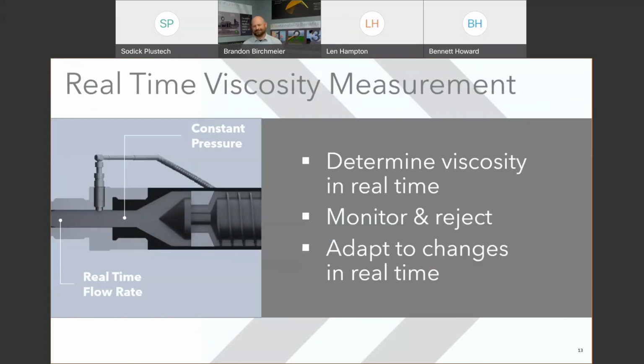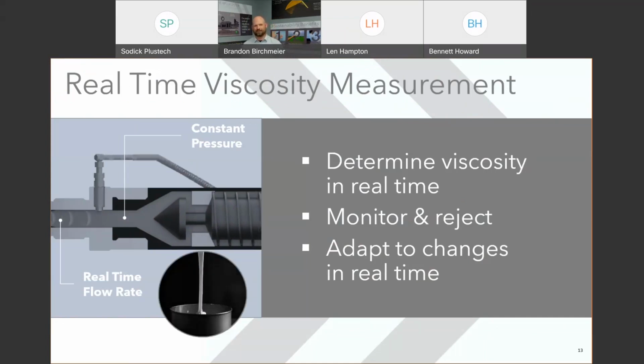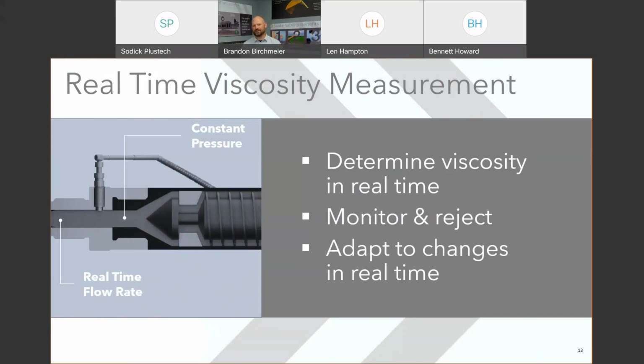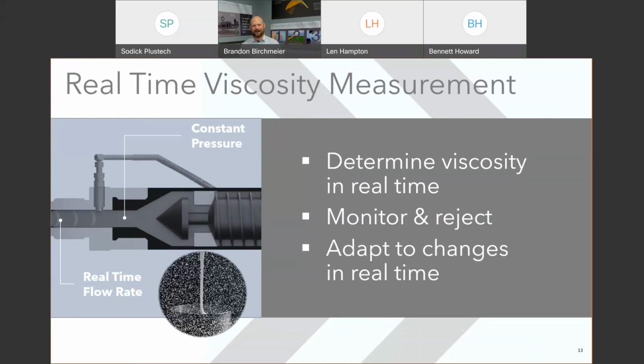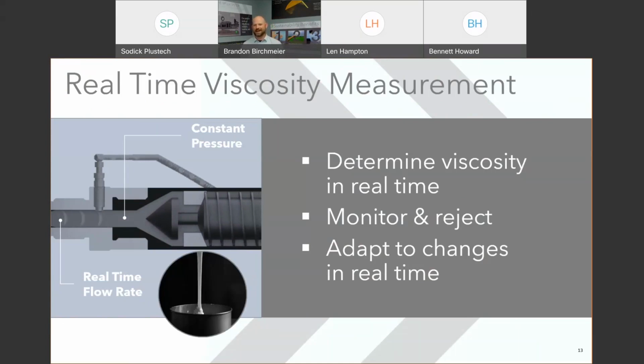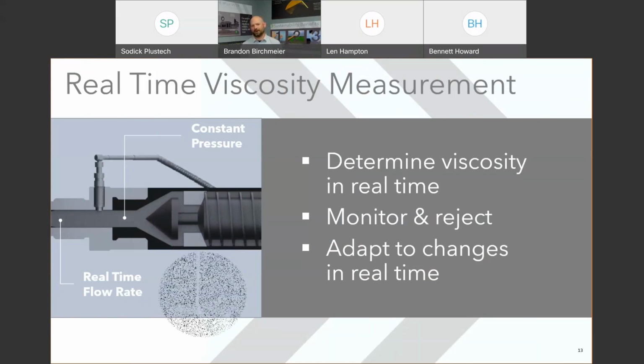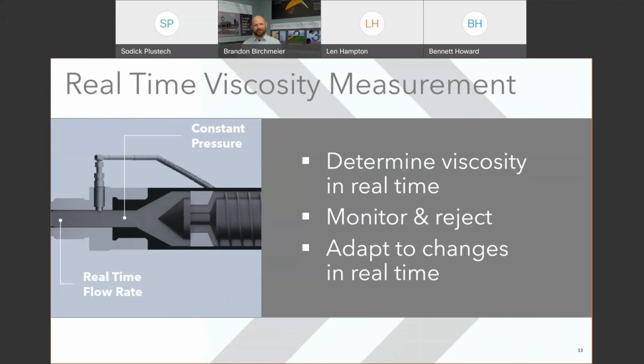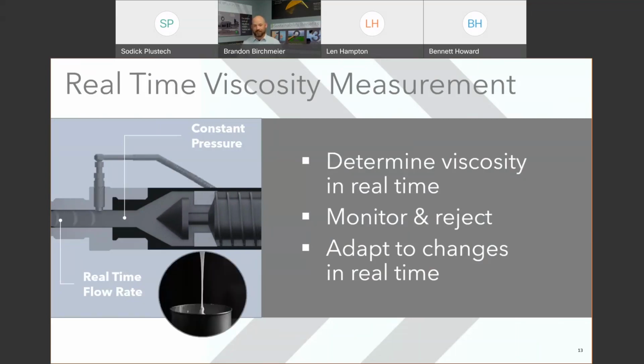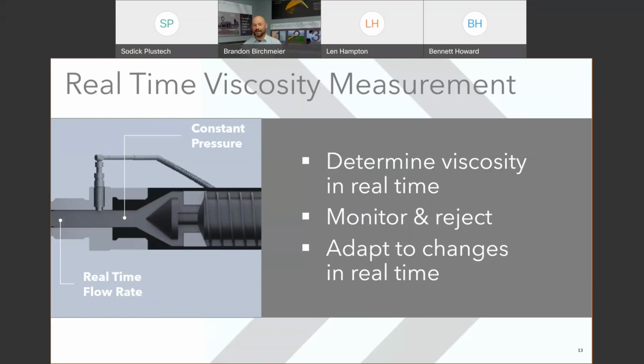One of the neat things about our technology, and what I love to talk about, is our auto viscosity adjust technology, which I'm going to start talking about now. So what's really interesting about using constant pressure in a barrel is it now mimics a rheometer. If any of you have gone out and tested MFI of your material, that test is done with constant pressure. It's not done with constant velocity. We actually use constant pressure to determine the melt flow index of the material. Well, I'm basically turning your barrel into a large diameter rheometer. Because I'm utilizing constant pressure, if I recognize these changes in the fill rate, I know something has happened in the viscosity. So I'm able to recognize those changes in real time and adapt to those changes in real time, which gives our technology some very unique advantages, especially as we start talking about recycled resins, sustainable resins, more wide spec resins.